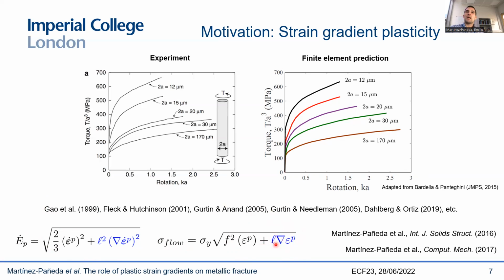And this length scale is a material parameter that somehow characterizes the ability of a material to harden in the presence of these geometrically necessary dislocations, of these plastic strain gradients. Because as you can see in the experiments, what these GNDs are doing is basically acting as obstacles to the movement of statistically stored dislocations, and therefore elevating the stresses. And the good news is that using these gradient plasticity theories and fitting this length scale, which you can think of as something like the strain hardening exponent, right? A material parameter that characterizes the hardening abilities of our material.